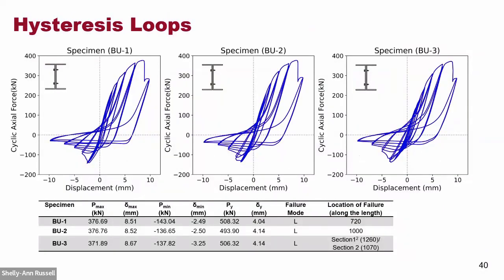The same happened with U sections, built-up columns. You can see the same asymmetric pinching behavior of these columns after buckling. So you can see the degradation of the stiffness and also the strength. But still, the tension was working and absorbing energy. And at this point, the same thing happened as in the C section. So you can see the yielding forces are almost the same. And you can see the compressive strength is a bit lower because U sections don't have these lips. So these lips change the compressive strength a lot. And because of that, we have these more innovative and optimized sections with stiffeners and lips in these areas.